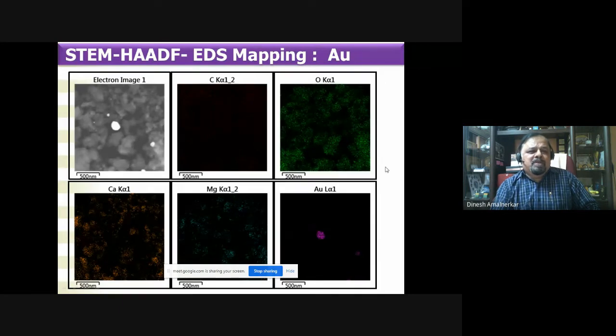Okay, now this is important. The STEM HAADF technique, as I said, acquires spatial resolution for atom to atom chemical mapping in the material. This is the STEM image, scanning transmission electron microscopic image. You can see a good contrast here, and this is definitely gold. Look at this color. This spot is gold, this is gold, this is gold, this is gold. You can see the spots here, here, here, everywhere.